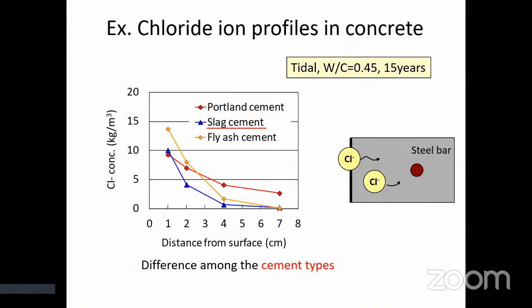This is an example of chloride ion profiles in concrete with different cement types. This figure shows results of Portland cement, slag cement, and fly ash cement. Chloride penetration depends on cement types. Especially, slag cement inhibits chloride ion penetration more than Portland cement. For this reason, blast furnace slag cement is generally used in concrete structures in Japan.